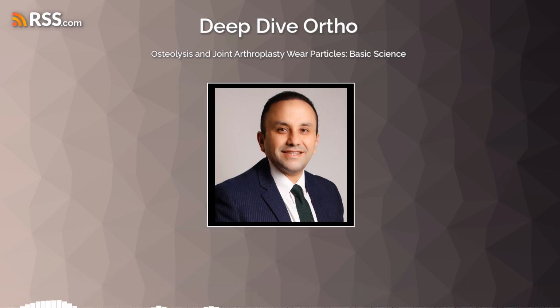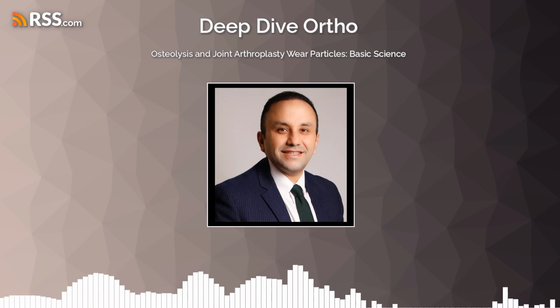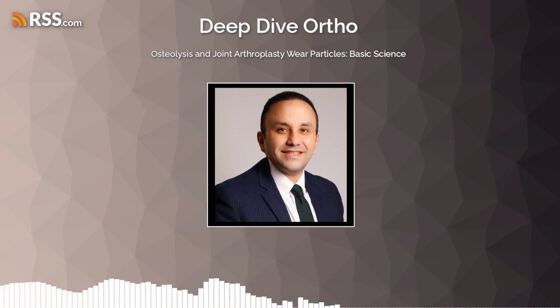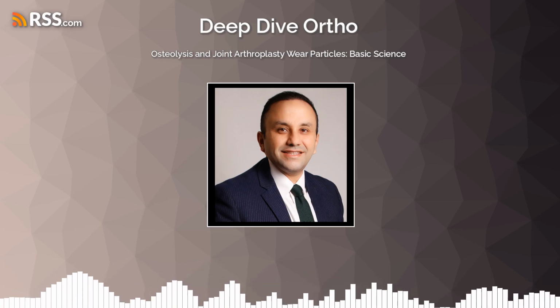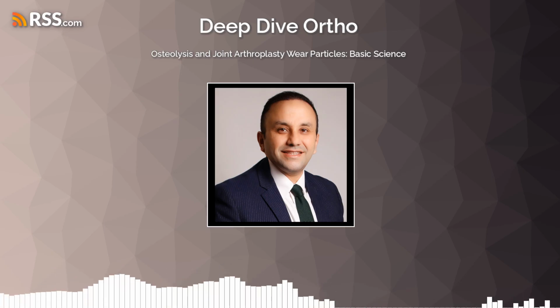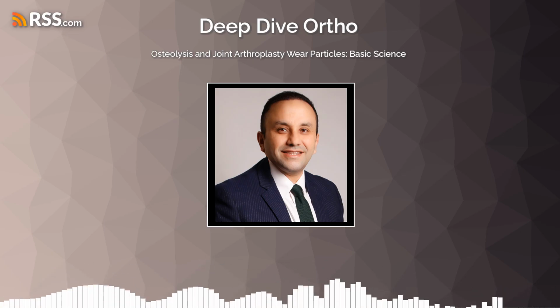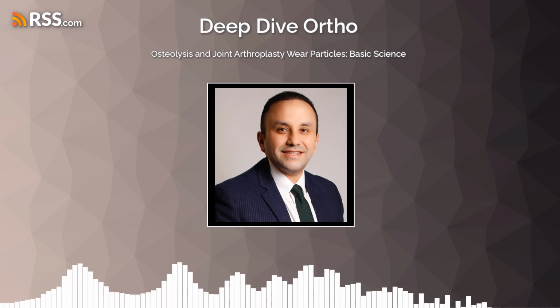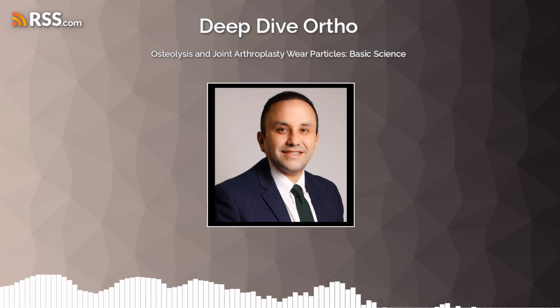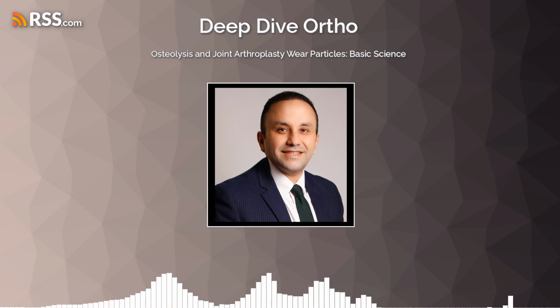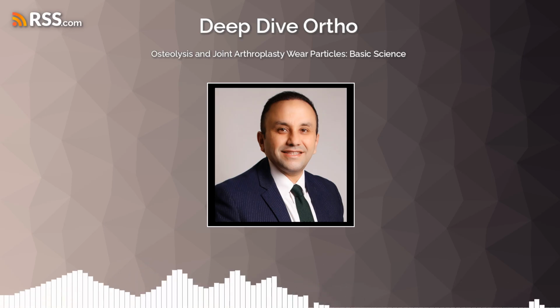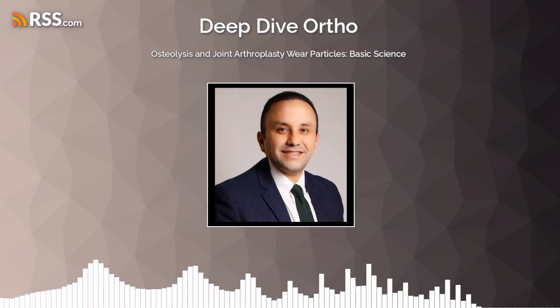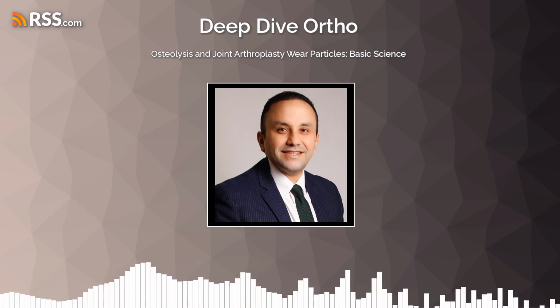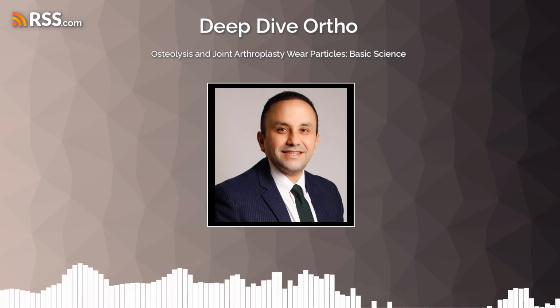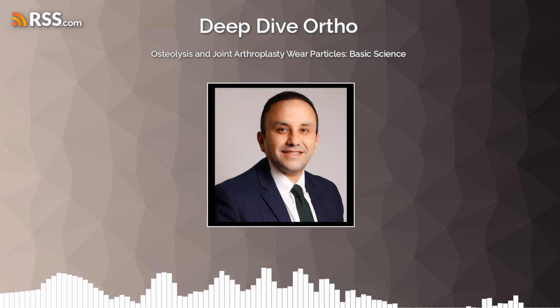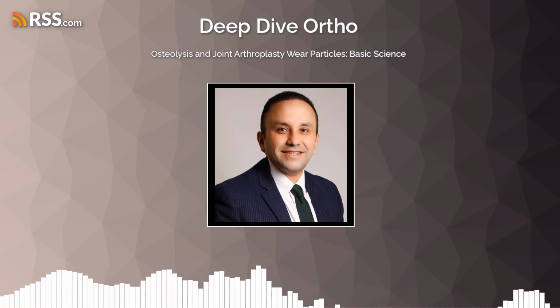If the stress is shielded or bypassed by a stiff implant, the adjacent bone undergoes resorption due to this lack of physiological stimulation. This can manifest as a more diffuse, often proximal bone loss around the femoral stem or other load-bearing components. So the bone just weakens because it doesn't think it's needed. In essence, yes. While it may not directly cause aseptic loosening initially, it can compromise bone stock over time, making it more vulnerable to particle-induced osteolysis later or complicating future revisions.